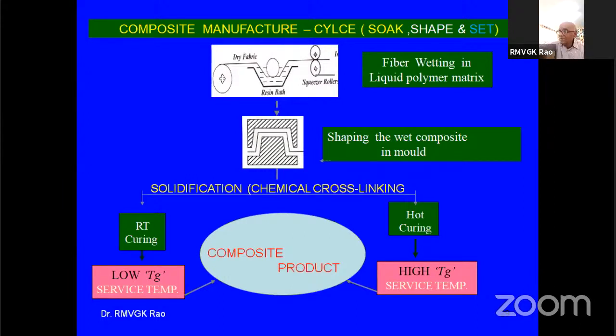But in the setting, there is a chemical cross-linking, which I'm going to show you next, where it completely becomes a 3-dimensional network of molecules after you add the hardener to the resin, impregnate the fibers and mold it into a mold like this and apply vacuum or pressure, whatever it is, and it cures. If you use a medium temperature hardener and a bifunctional epoxy, you get a lower glass transition temperature like 120, which you use in Hamsa. But if you go to a multi-functional epoxy with more active groups, and cure it with an aromatic amine, a higher order amine, then you get a higher glass transition temperature like 160 and above. Therefore, the service temperature limits are governed by the method of curing, by the choice of the functionality of the matrix.